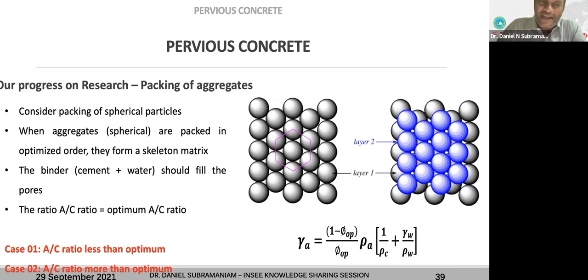Now when you talk about aggregate packing, if you pack the aggregates in an optimum way, beyond that you will not be able to pack them further. For example, in materials we would have learned about atomic packings: BCC, the body centered, or face centered, HCP, and there are so many others, and the simple cube. Beyond that point, you will not be able to pack further, so the pores will remain free. Now, for a pervious or conventional concrete to have an optimum aggregate to cement ratio, when all the aggregates are packed in an optimal way, the binder should be able to occupy all the spaces in between. Based on that concept, we should be able to have an optimum aggregate to cement ratio for any pervious concrete.